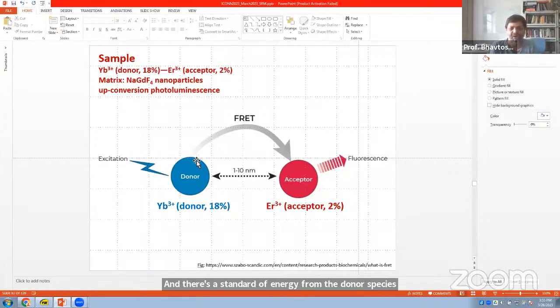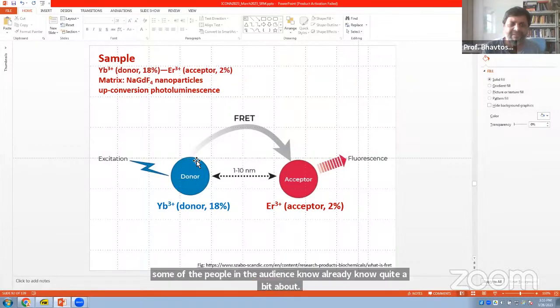It works if the distance between these two is of the order of 10 nanometers or so, and it has a very strong dependence on the distance, like 1 upon R to the power 6. One of the well-known systems, which some of the people in the audience may already know quite a bit about, are the lanthanide ions. For instance, ytterbium and erbium ions are a very popular combination of lanthanides, where Yb3+ acts like a donor and erbium acts like an acceptor.